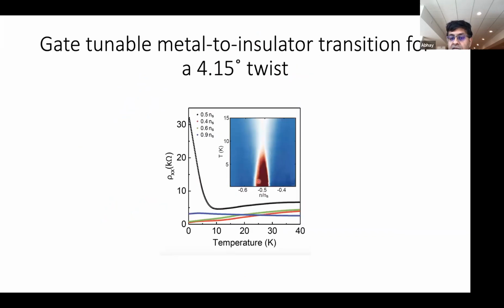And what we observed is, like twisted bilayer graphene, as you tune the density, and this is in units of filling of the moiré unit cell, as you go to half filling of the moiré unit cell, you observe an insulating state. So dark here means insulator, the dark red, and the blue here is metallic. And as you lower the temperature, you enter an insulating state at fairly low temperature, on the order of 10 Kelvin, at precisely half filling, like twisted bilayer graphene.